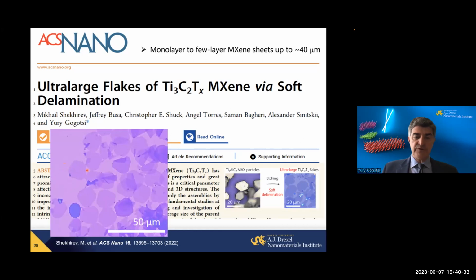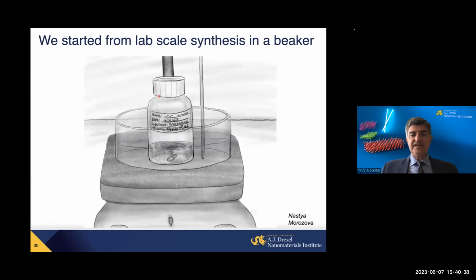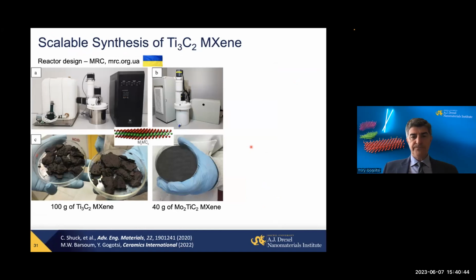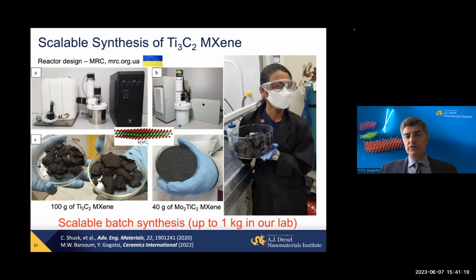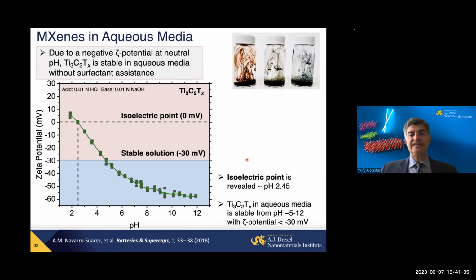Now, we started making MXene in a beaker, as one of my students showed in this hand-drawn picture. However, we now use reactors. Actually, these reactors were designed by us, by a company my brother founded, Materials Center, and we can make up to 100 grams per batch of materials. You see here titanium 3C2, and here 40 grams of atomic sandwich MXene, like molybdenum-2 titanium C2. It doesn't matter which one, more exotic or more common, you can make it in quantities. And this is one of my students, Gita Valoroso, holding 1 kilogram of titanium 3C2 MXene produced within 24 hours in our lab. Within the next 44 hours, it was completely delaminated into two-dimensional single to few layer flakes.